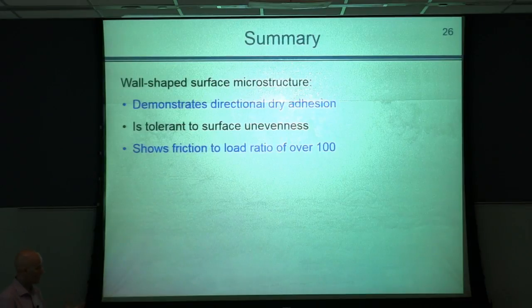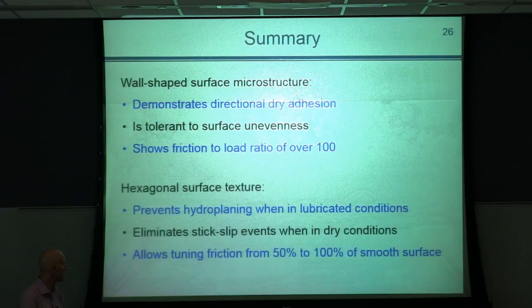And this is more or less also to summarize. We worked with wall-shaped microstructures that are able to demonstrate directional adhesion and are tolerant to surface roughness, and are able to generate really high friction. And hexagonal surface textures are found to prevent hydroplaning when in lubricated conditions.